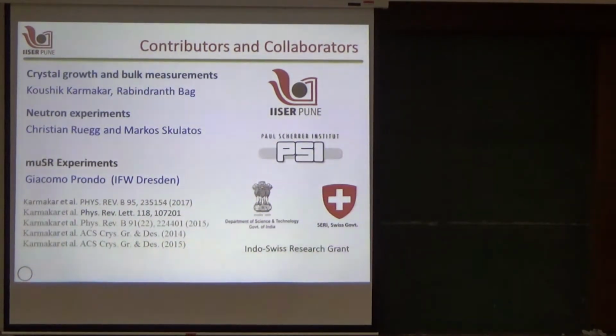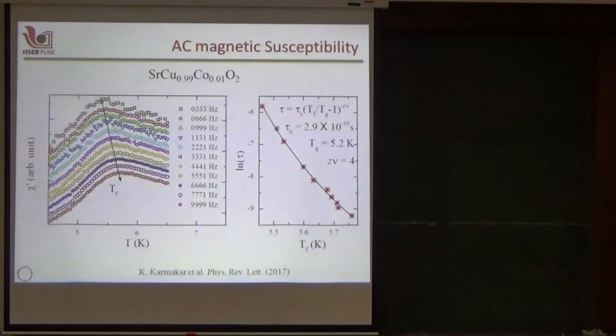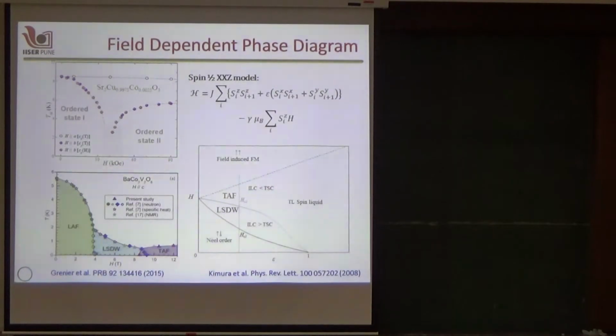On this phase diagram, experimentally, how can you incorporate the effect of epsilon by impurity concentration? That's what I tried to show, that by doping cobalt impurities, cobalt is known to have, unlike copper, where the orbital angular momentum is fully quenched and therefore the spin is isotropic, in the cobalt case, cobalt salts are known to show highly anisotropic properties. So what we believe is that this anisotropy of the cobalt is getting induced in the whole chain, but it's very surprising that such small concentrations can change the behavior of the bulk.